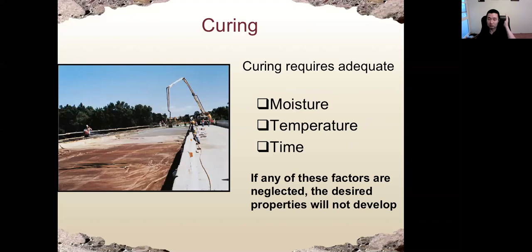A good curing requires 3 things: one is moisture, the water; the second is temperature, cannot be too low or too high; and the third is time, which should be long enough, at least 5 to 7 days. If any of these 3 factors - moisture, temperature, and time - is missing, the design property may not be achieved. This is very important. Even if you design very good concrete and cast and compact it perfectly, if the curing is not there, the strength and other properties cannot be achieved. So curing is very important.